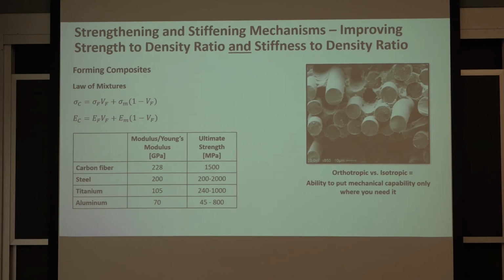You've heard of carbon fiber and fiberglass. There are also metal matrix composites, where you put in a fiber that is more compatible with the metal. I once worked on a project where we put aluminum oxide fibers into aluminum, called Nextel fibers. They're incredibly stiff, and putting them in aluminum can increase the stiffness by at least a factor of 2. We did some experiments at Chrysler where we made brake calipers using this method. It didn't go into production, but it worked.